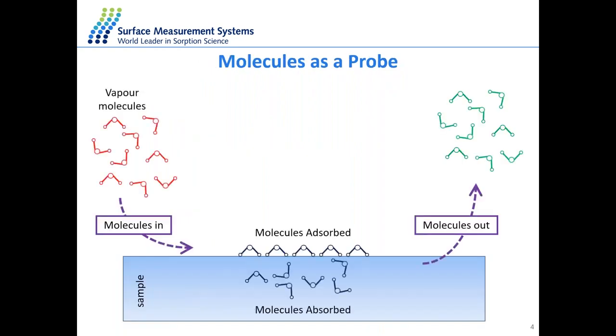So when we're using molecules as a probe, what happens in the DVS system is we inject or introduce our vapor molecules onto the surface of our sample. And depending on the interaction between the sample and the molecules, the molecules can either be adsorbed on the surface of the sample or be transferred into the bulk of the sample. The molecules can be absorbed into the bulk of the sample. This is the sorption process. We'll also have a desorption process where the molecules are released out from the sample.